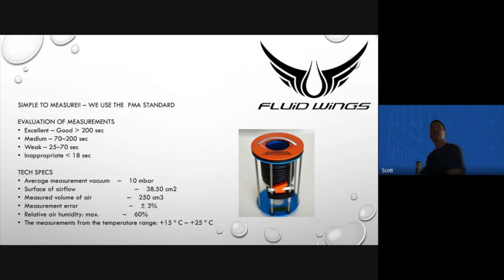So if you get one back and someone says it took 1,000 seconds, that's really good. New fabric will be anywhere from 500 to 2,000. 70 to 200 seconds is okay, it's good. Midlife, midwear. Again, this isn't going to dictate performance necessarily, but it's a corollary, and it's the one thing we can measure really well. Obviously, when you start getting down around 30 seconds to a minute, not so good.